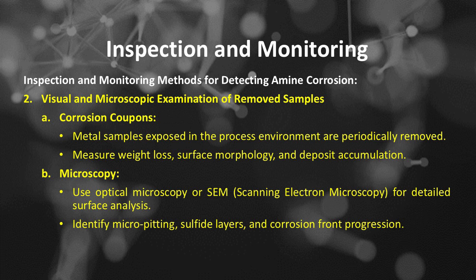Inspection and monitoring methods. Number 2 is visual and microscopic examination of removed samples, which includes, the first, using corrosion coupons. Metal samples exposed in the process environment are periodically removed. Measure weight loss, surface morphology, and deposit accumulation. The second is using microscopy, using optical microscopy or SEM, scanning electron microscopy, for detailed surface analysis. Identify micropitting, sulfide layers, and corrosion front progression.